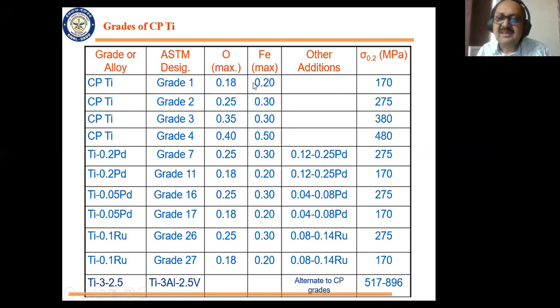Oxygen dissolves very well in titanium. A large amount of it does dissolve, and it is one of the main strengtheners. Although it also embrittles, it is used as a strengthening agent, and you can see it here. As you are increasing the oxygen, these yield strength levels are going up. So there are several grades of CP titanium depending on what oxygen levels you want. And then, as I told you, palladium addition also improves corrosion.